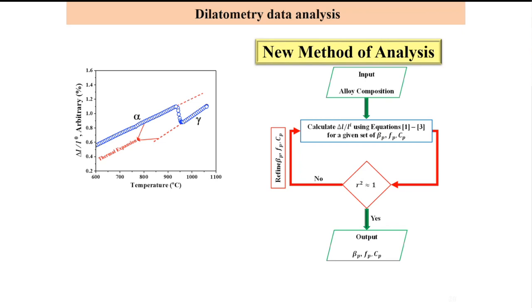To simplify: length change is proportional to the fraction of phases, the composition of phases, the lattice parameter of unalloyed material, thermal expansion coefficient, and temperature. We developed an iterative process where this is calculated starting from guess values, and when we get a very good match between the experimental dilatation curve and the calculated ones, we obtain the fraction of phases and the composition in terms of carbon concentration, assuming parallel transformation. We begin with martensite transformation because the parent and product phases have the same composition, giving one less variable to deal with.